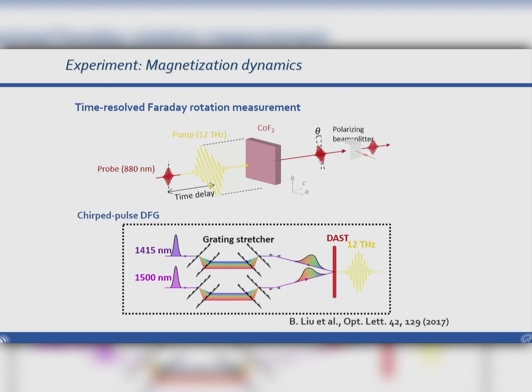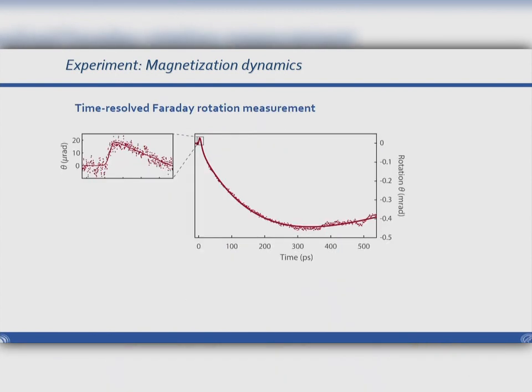So therefore, and this is why, this mid-IR pulse is slightly rotated away from the optical axis. And what we observe in this Faraday rotation measurement is, first, a small blip at time 0, which we believe is a result of optical birefringence induced by the phonons itself. But then on the longer scale, you see a rotation of the polarization that's indicative of a change in the magnetization of the sample, relating to the induction of a magnetic moment.